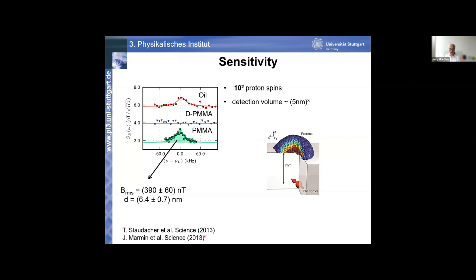And we did this now almost exactly 10 years ago. And in the meantime, people have very much worked on improving the sensitivity. There are now experiments on single nuclear spins where people really see the magnetic resonance or NMR signal of single proton and carbon spins and so on and so forth. So it has matured and developed into a technique where people try really to do this for chemical structure analysis.